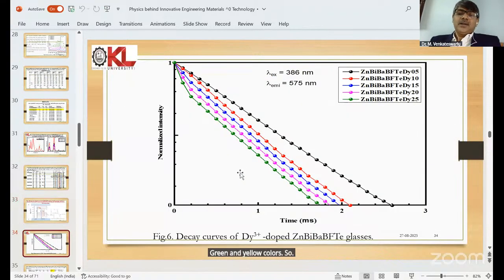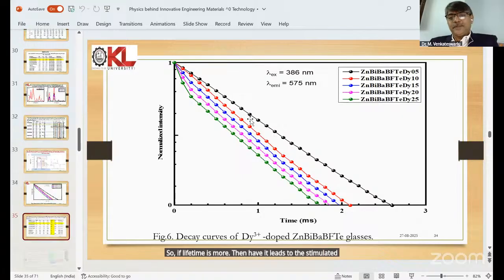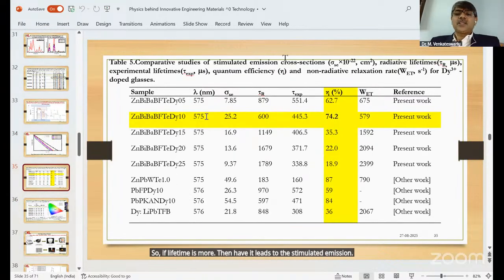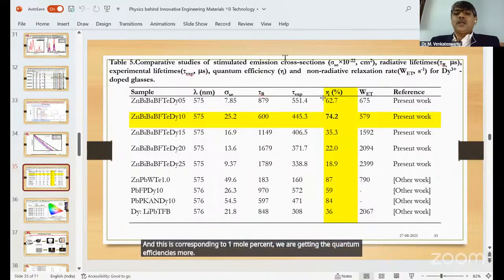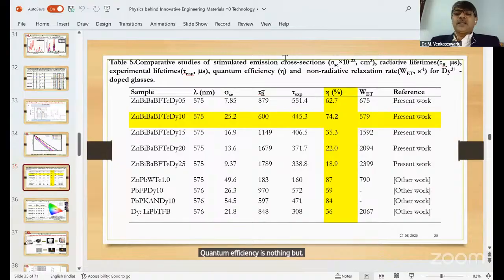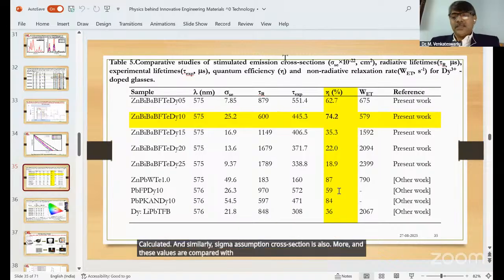So these are the decay curves. Decay curves indicate how much time those ions spend in the excited state. If the lifetime is more, it leads to stimulated emission. And this corresponds to 1 mole percent. We are getting higher quantum efficiency. Quantum efficiency is nothing but tau experimental divided by tau radiative. And similarly, the emission cross section sigma SE is also more. And these values are compared with the literature survey.